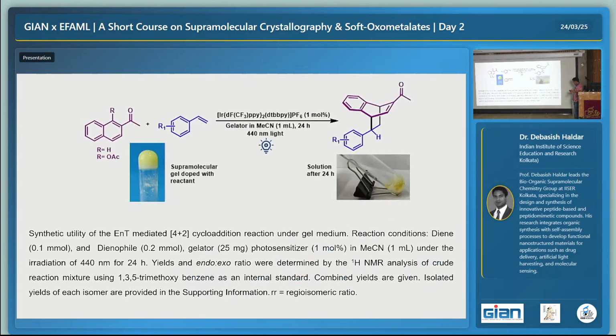And so then we thought, okay, let's do the reaction. So we have taken our gelator in acetonitrile, just using that acetonitrile from our solvent purification system, and no degassing, nothing. And then we have used our material, put it all together with this catalyst, and then we just sonicate it. So immediately it forms gel, and due to this catalyst, now it looks a little bit yellow, otherwise the gel is white in color.